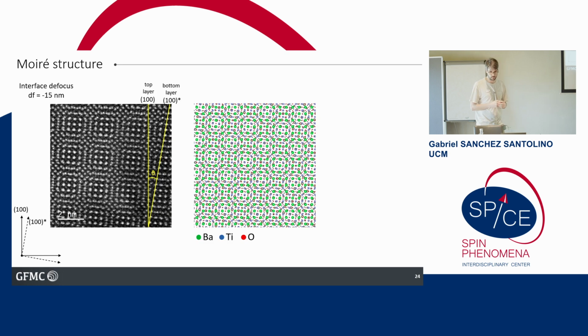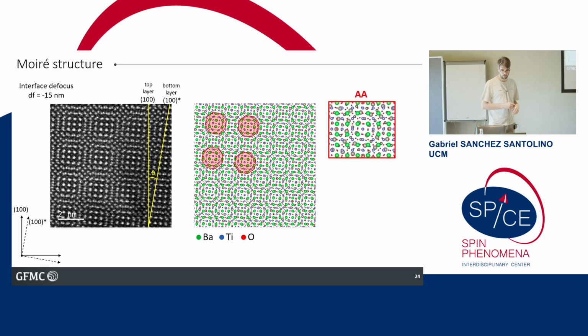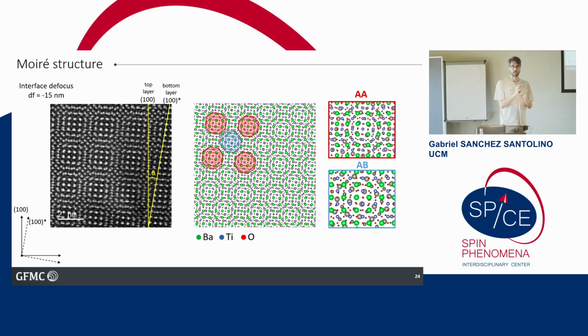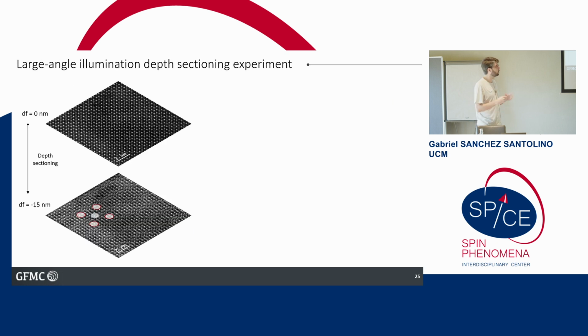We have a very similar structure to what we get when we twist any other 2D material, and these are two layers that are twisted by 10 degrees. So we have these Moiré features here, and this is the model of the two twisted layers. I'm going to refer to two structures within the Moiré, which are these AA and AB stacking regions, where we have highly coincident sites between the titanium atoms on the top and titanium atoms on the bottom, or, in the AB, titanium atoms on the top and barium atoms on the bottom, right? So we have these two kinds of structures that form a Moiré lattice in our twisted bilayers.